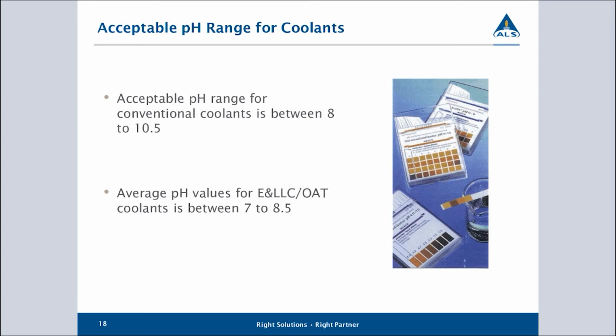So for our conventional coolants, the older style coolants, somewhere between 8 to 10 would be a typical range. You very seldom see them as high as 10 nowadays. All the newer formulations tend to run between 8 to 9 maximum. And it's unusual to see a coolant go up to 10 now.